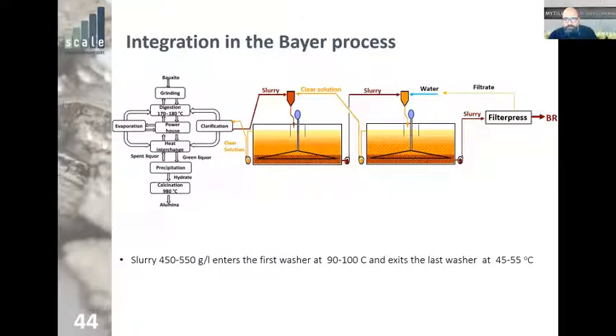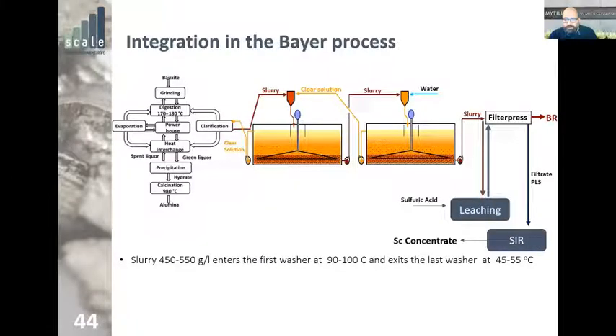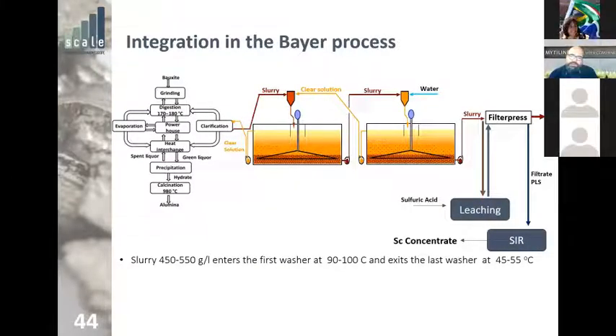So we can imagine how we could intervene with this scandium leaching process just after the last washer and before the filter press. Basically, you would add another reactor there that would have the same capacity as the washers. And in this reactor, you would do sulfuric acid leaching, then drive everything to the filter press. The filtrate, instead of being remixed with the water in the last washer, would constitute the pregnant leach solution out of which the ion exchange process would take out the scandium.